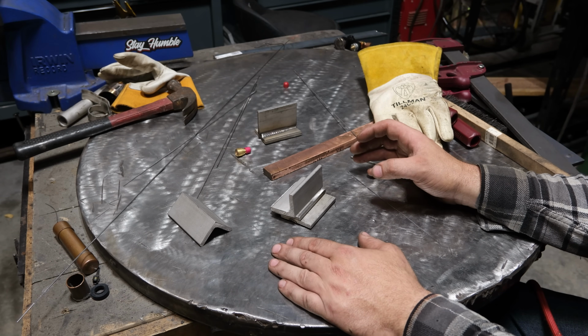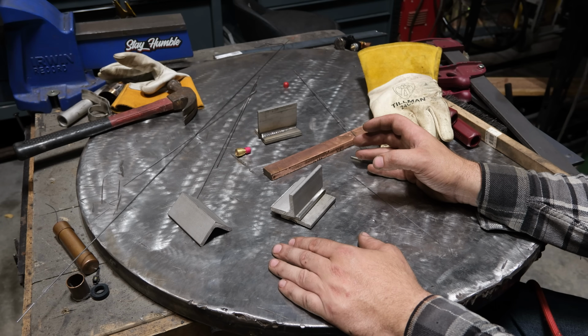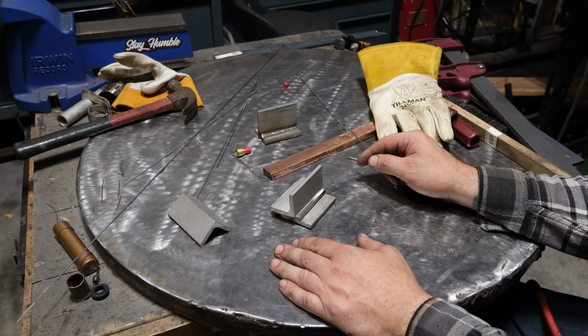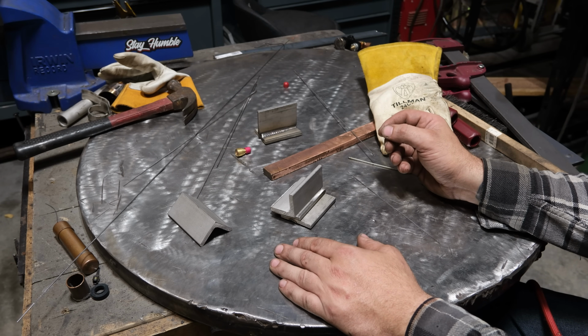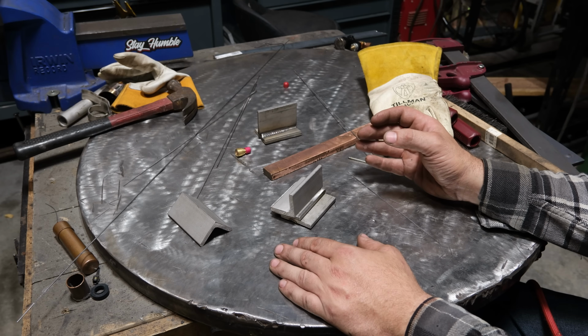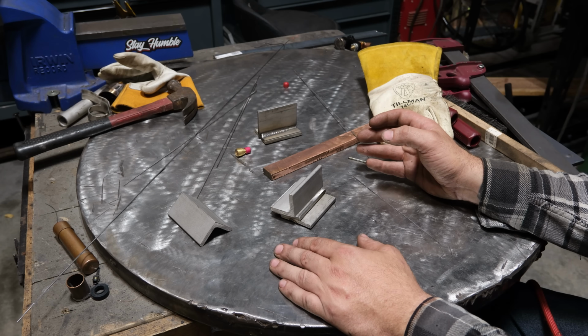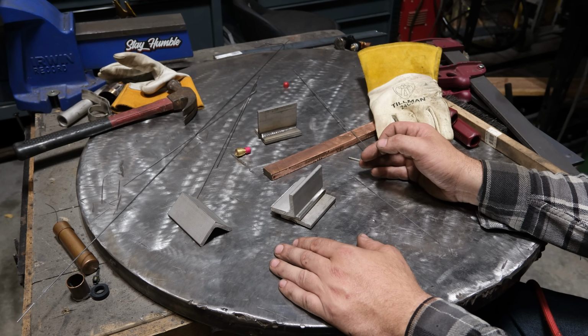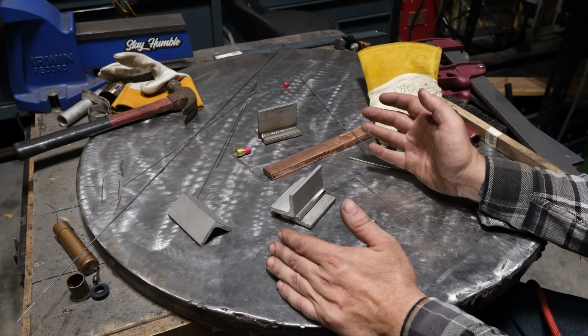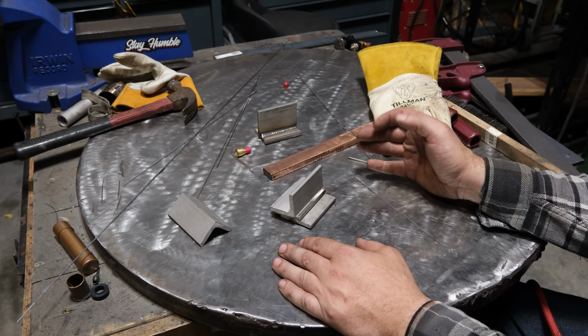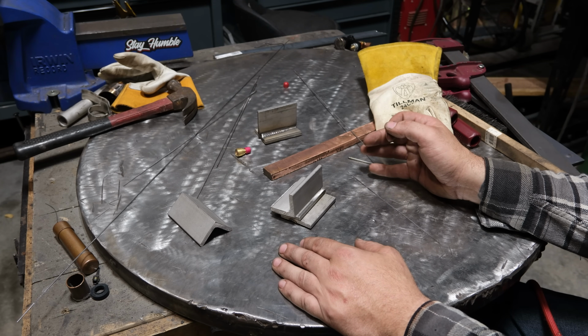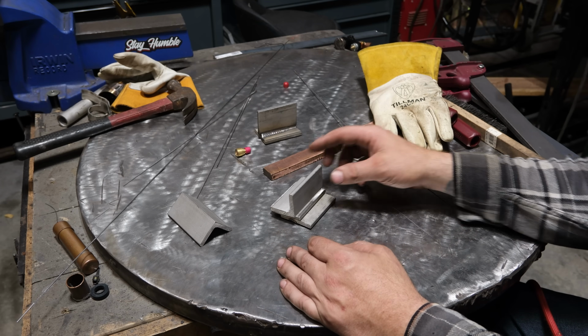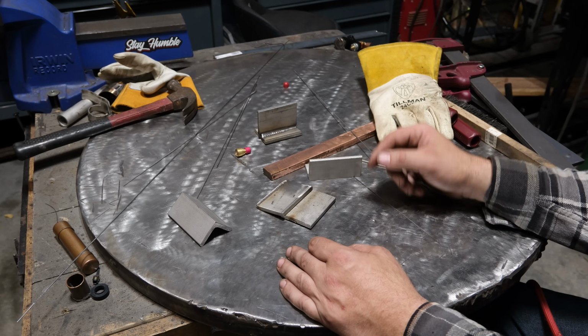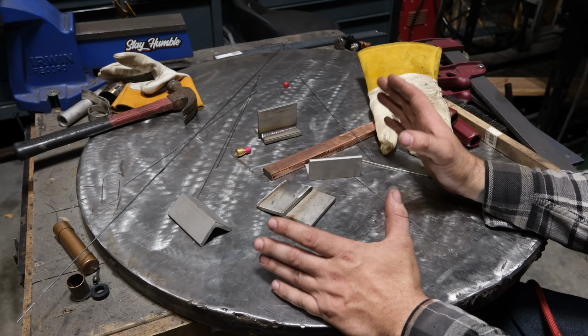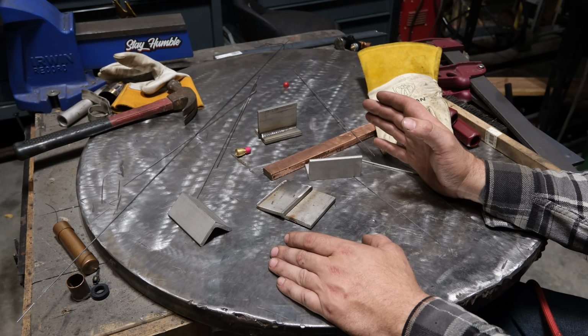Another thing that's worth mentioning is the oxide on the backside of a weld. On that thin material, that stuff is reacting in that molten puddle, because that molten puddle is basically all the way through the material, and it will influence the puddle on the front side. So by not back purging, which by the way I'll have a whole video on, by not back purging thinner material, it's going to weld poorer on the front side. It's just the nature. On thicker stuff like you saw on this that I broke in that one, it welds perfectly fine. The lack of back purge doesn't affect it.